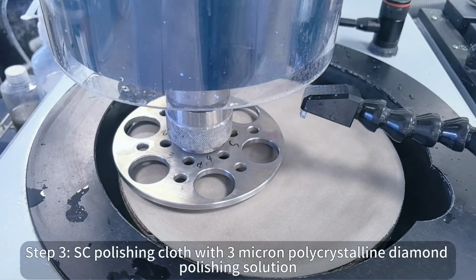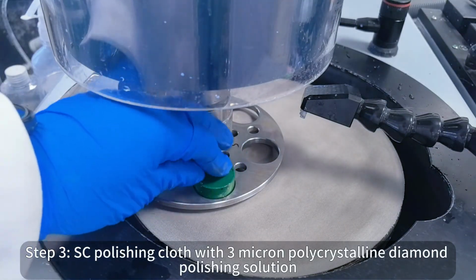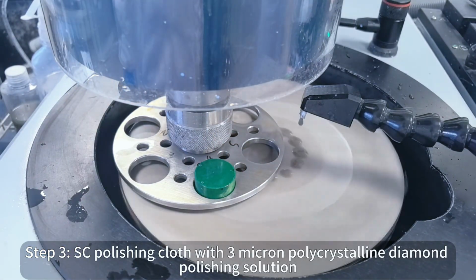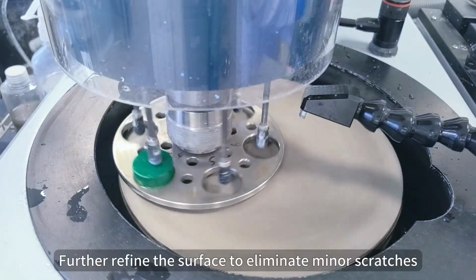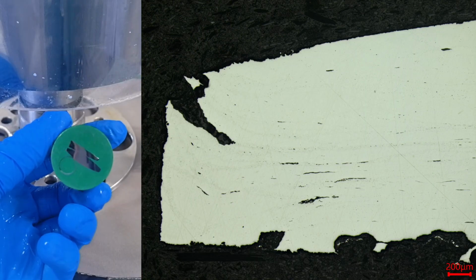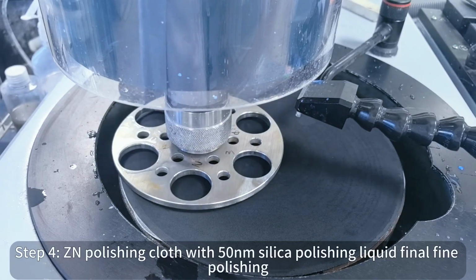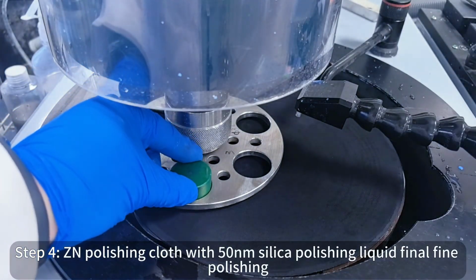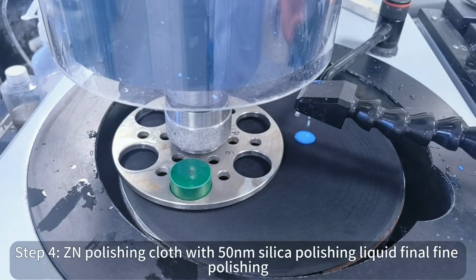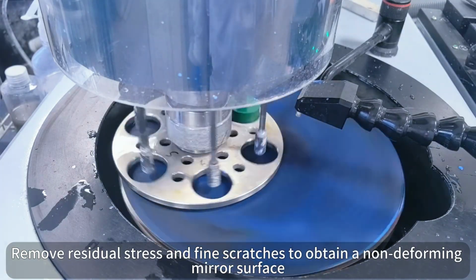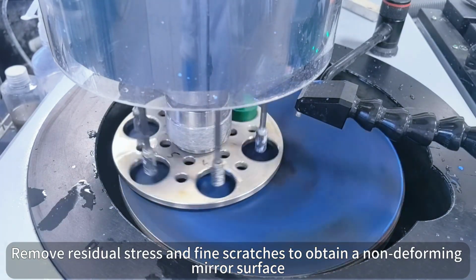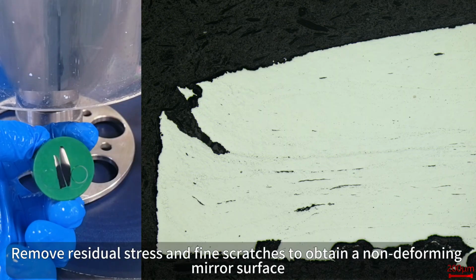Step 3. SC polishing cloth with 3-micron polycrystalline diamond polishing solution. Further refine the surface to eliminate minor scratches. Step 4. ZN polishing cloth with 50 nanometer silica polishing liquid for final fine polishing. Remove residual stress and fine scratches to obtain a non-deforming mirror surface.